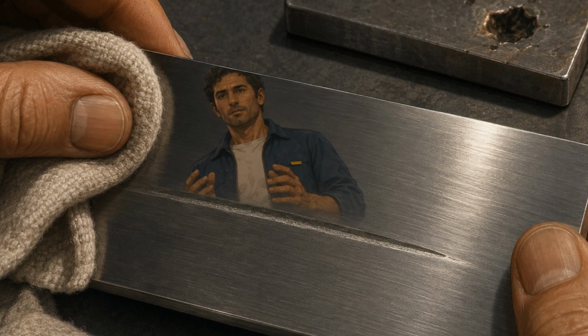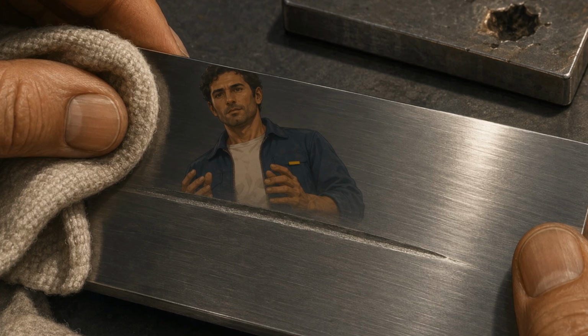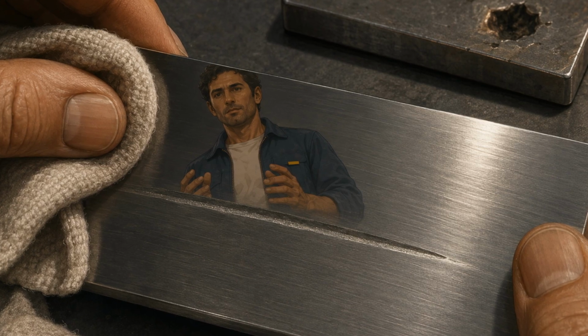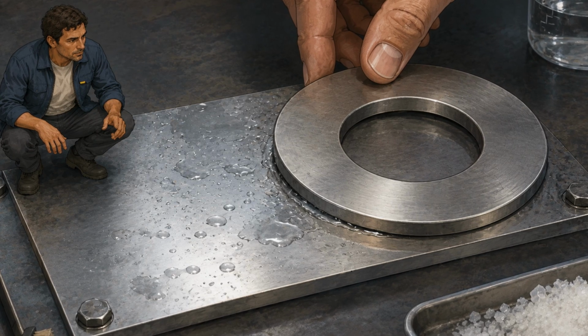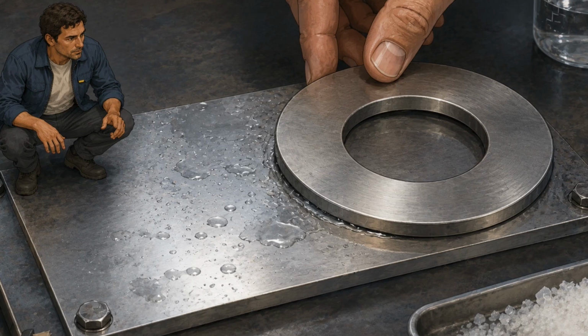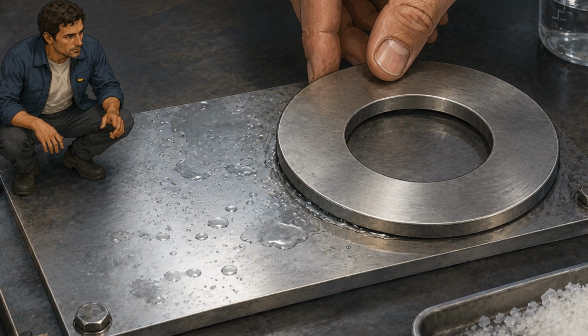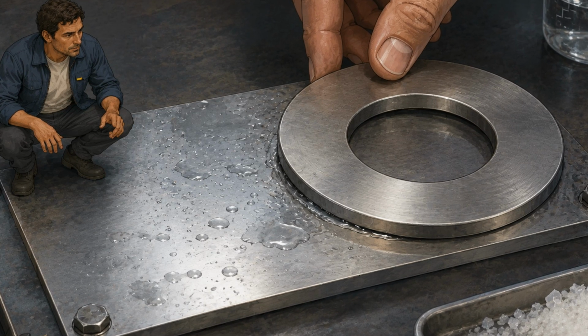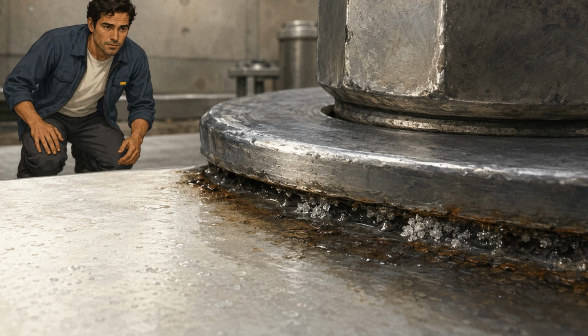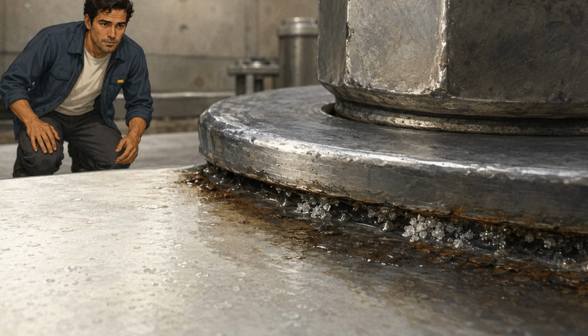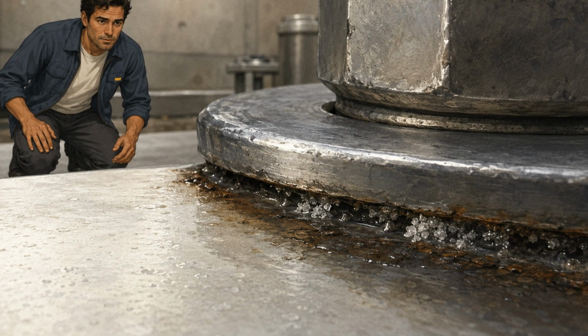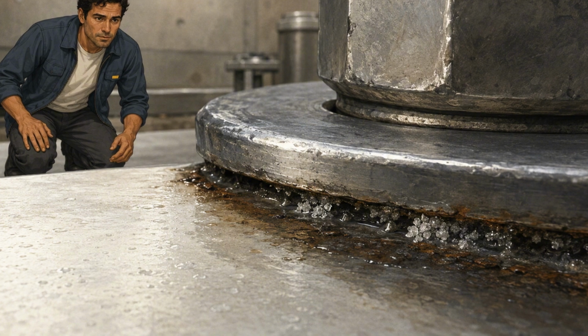The scratch itself remains. Stainless steel does not grow back like skin, and a deep pit does not fill itself. The repair also needs favorable surroundings. On an open, clean surface, oxygen can support the passive state. Inside a tight, wet gap, the local environment may change faster than it can recover. Imagine salt water trapped beneath a washer. Oxygen inside the gap is consumed and replenished slowly. The liquid becomes more acidic and chloride-rich, weakening protection inside while the open surface still looks bright.